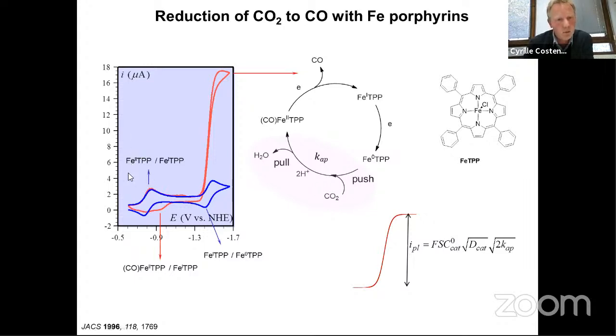If you start with iron 2 porphyrins, you can reduce it twice, and you can see that in the presence of CO2, now you have a catalytic process at the level of iron 1, iron 0 porphyrin. And you can see that the current is important and it's almost a plateau here. If you run a bulk electrolysis in this situation, you can show that the Faradic efficiency for the production of CO is close to 100%. So no hydrogen or little hydrogen is produced, mainly CO as a product,